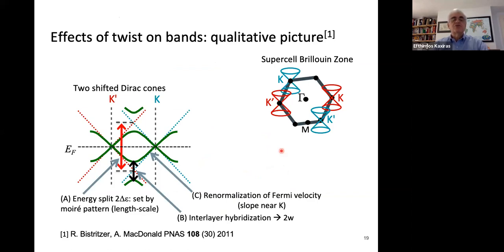So the first question is, what are the effects of the twist on the bands? And I'll start with a qualitative picture, and I must give credit here to Allan MacDonald and his co-workers who first put together this very important basic qualitative picture of what is happening. So here again is the supercell Brillouin zone that I showed you a moment ago with the two sets of Dirac cones, one from one layer, the blue one, and another from the other layer, the red one. And here they are again. These are now cross sections of the Dirac cones.